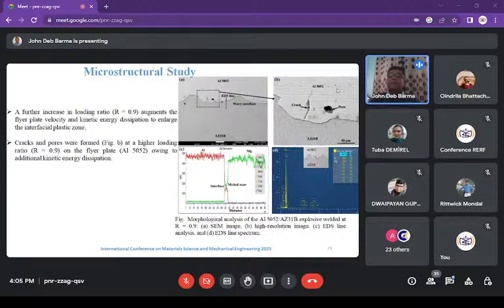And here you can see that this flyer plate, that is aluminium 5052, experienced the dynamic impact. So as you can see in figure C, the EDS analysis showed more atomic diffusion here in the aluminium alloy as well as magnesium alloy than whatever has been observed at, sorry, R 0.7 and 0.8. And this is because at an increase in the loading ratio, that is at 0.9, it enhanced the kinetic energy dissipation at the interface, leading to an increase in the plastic deformation at the interface, as I've already mentioned earlier.